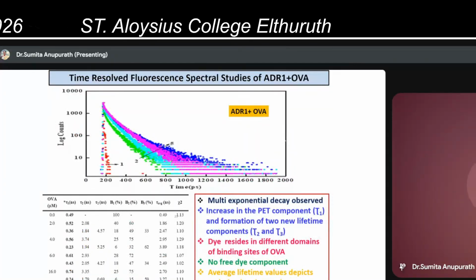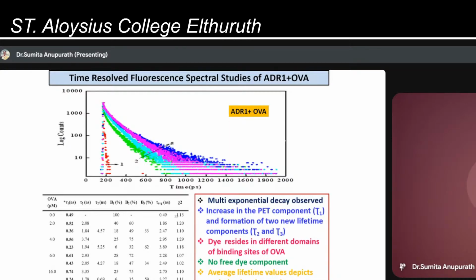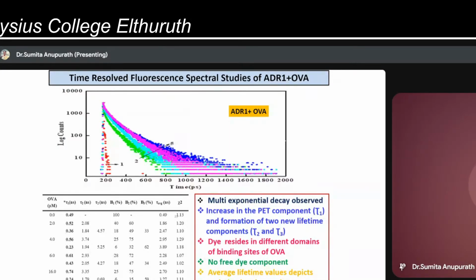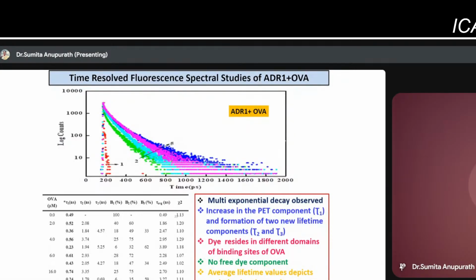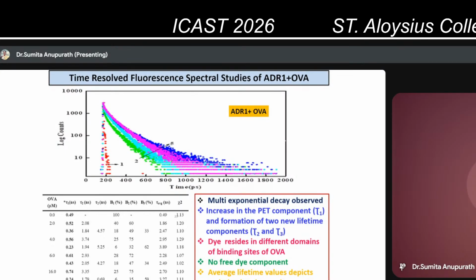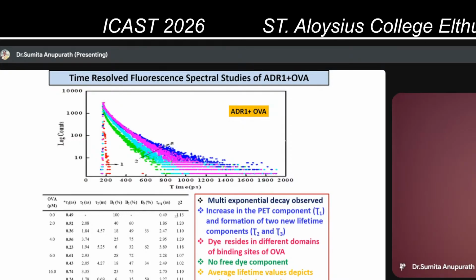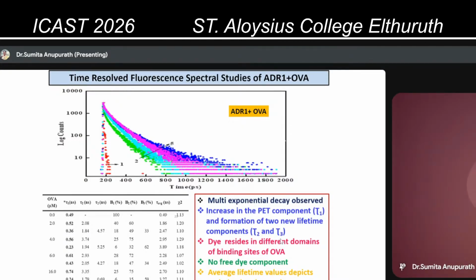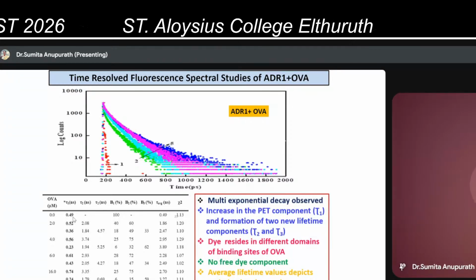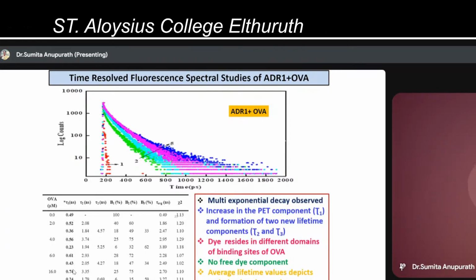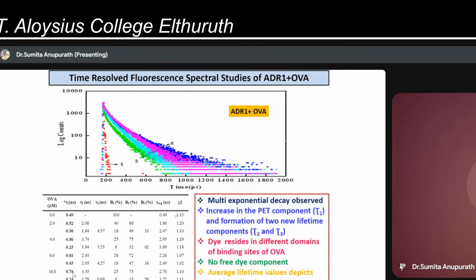Time-resolved fluorescence spectral studies of the ADR1 dye with ovalbumin showed that the single exponential decay of the dye changed into multi-exponential decay. And this shift from single to multi-exponential is due to the introduction of the protein to the system, which creates several distinguishable microenvironments around the dye molecules. Similarly, the PET component tau1 increased from 490 picoseconds to 740 picoseconds. That is, the PET process is completely suppressed.